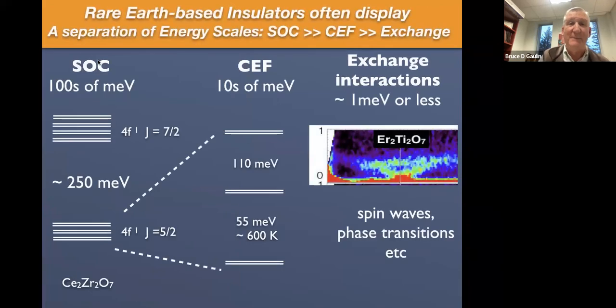Okay, so one of the nice things about studying these particular materials is that they're rare earth-based insulators, and it's often the case that there's a very nice separation of energy scales for studying any problem based on rare earth insulators, and my group has studied a fair number of them. One of the things that's attractive about them is that because the rare earth ions lie at the bottom of the periodic table, spin orbit coupling is relatively strong. The energy scale is hundreds of millielectron volts. So we know that the Hund's rule ground state is J equals 5/2.